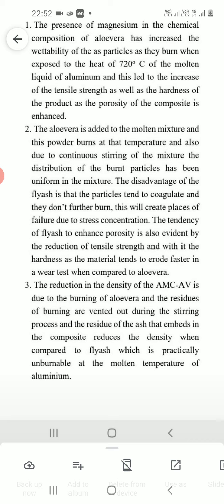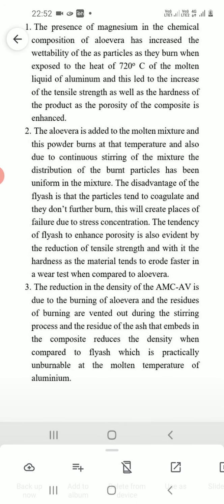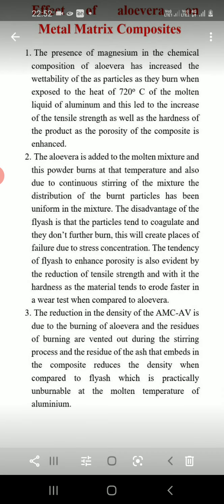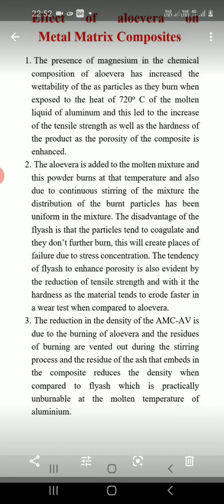Thirdly, the reduction in the density of the aluminum metal matrix composite with aloe vera is due to the burning of aloe vera, and the residues of burning are vented out during the stirring process. The residue of the ash that embeds in the composite reduces the density when compared to fly ash, which is practically unburnable at the molten temperature of aluminium. If we thoroughly observe these three points, these are the reasons behind the enhancement of mechanical properties of aluminium with aloe vera as a reinforcement composite.